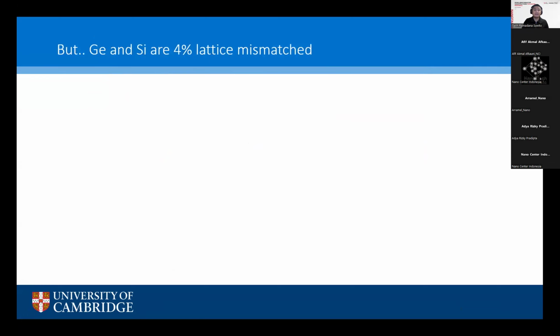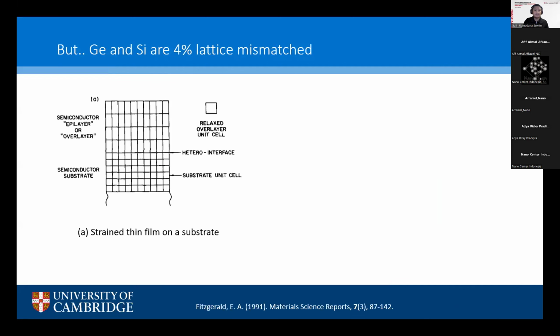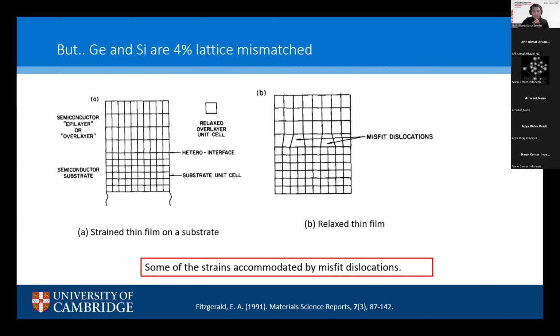Okay. However, germanium and silicon have a 4% lattice mismatch, and this is because the germanium crystal has a larger lattice constant than that of silicon. So this is what happens when you try to grow a very thin layer of germanium on silicon. You will get strained germanium, because the larger atomic spacing of germanium now tries to follow that of silicon. However, when you increase your epi layer thickness such that it's now larger than some critical value, misfit dislocations are generated to accommodate this strain. In this case, we call our germanium epi layer relaxed. So some strain is accommodated by misfit dislocations.